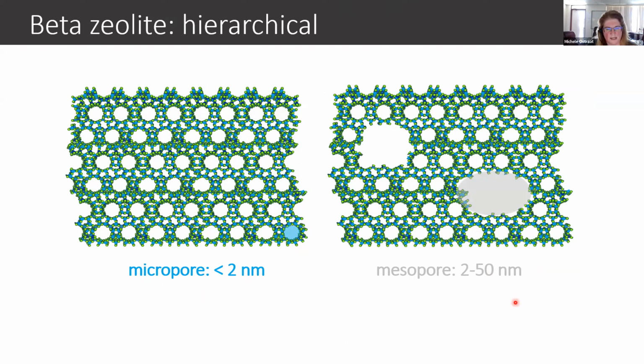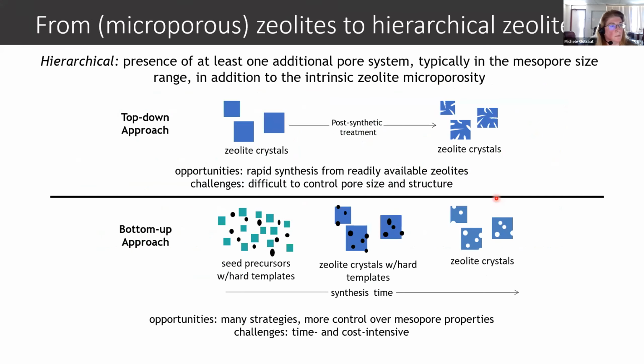And the challenge here is to be able to engineer in mesoporous pores that can extend beyond 2 nanometers upwards of about 50. And that would allow these big, large asphaltene molecules that might be 5 to 10 nanometers in size to be able to actually penetrate into these catalyst materials to be able to have exciting chemistry performed. There are a number of ways to be able to make hierarchical zeolites.